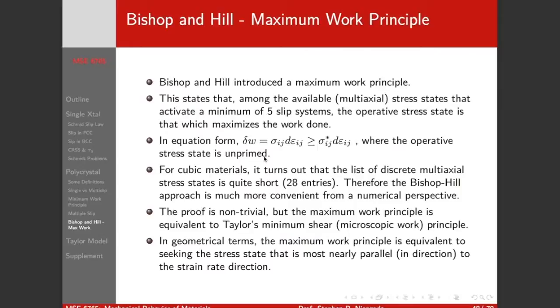So in 1951, Bishop and Hill introduced a maximum work principle. This maximum work principle says that out of all the available multi-axial stress states that activate a minimum of five slip systems, the one that is operative is going to be the one that maximizes the work done.